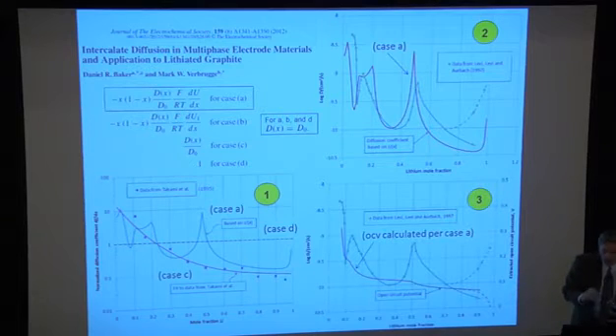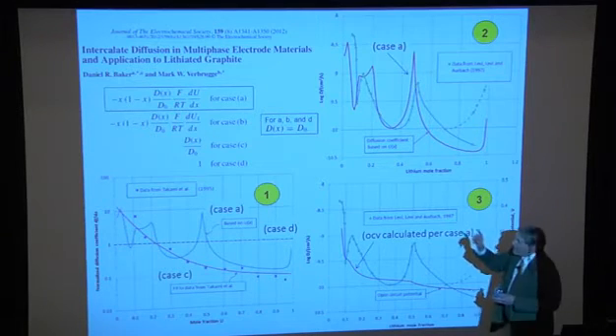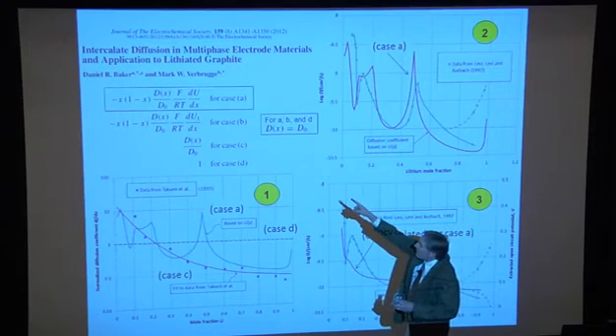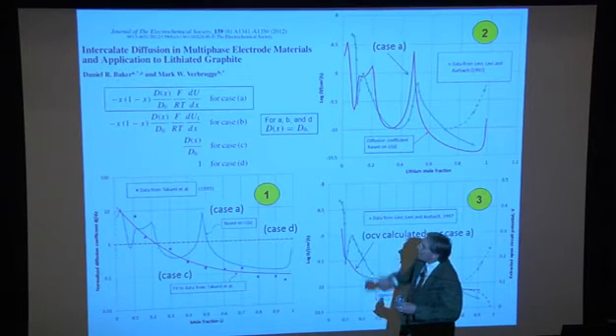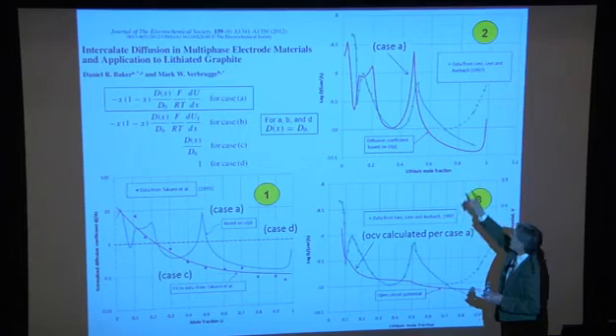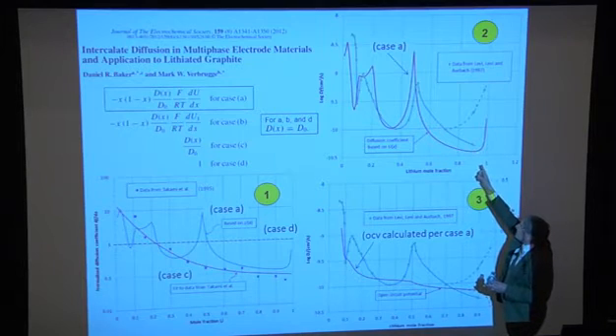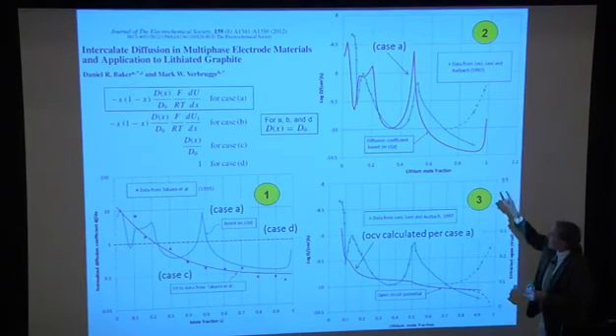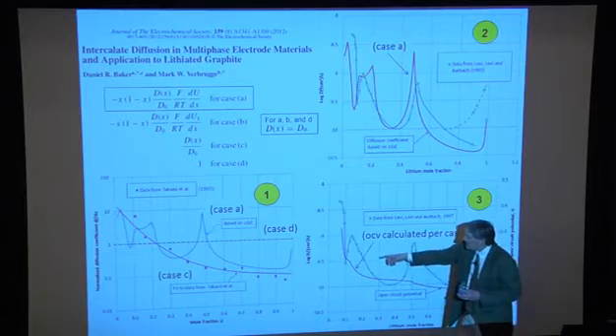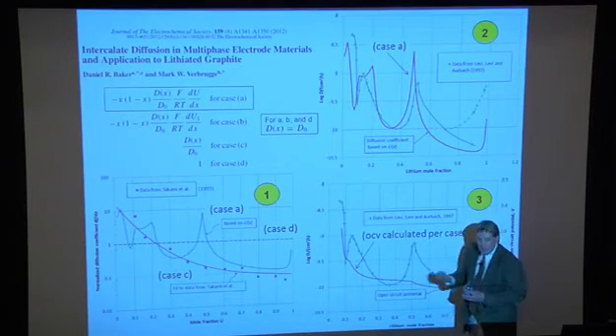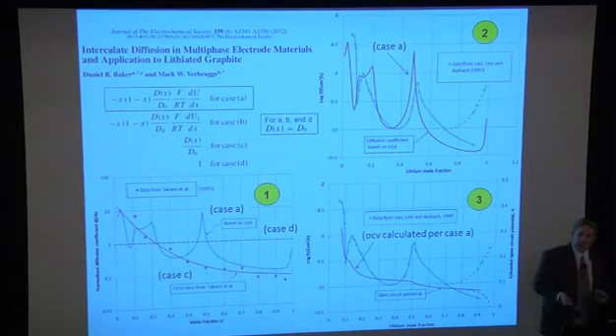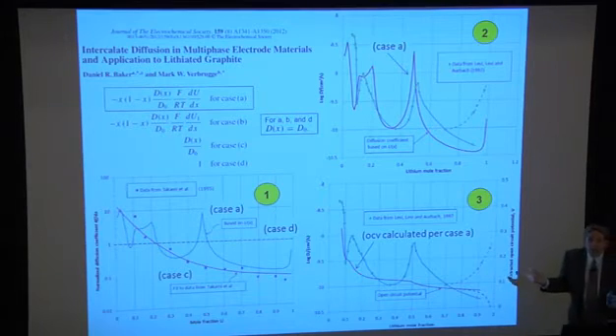And last, you can see in that top expression that you can integrate du by dx. So integrate Aurbach's data, from Lee, Levi, and Aurbach, and you can then calculate an open circuit potential. And that's what this red curve is. You're actually taking the transport measurements and back calculating a thermodynamic quantity, because we didn't have their open circuit potential